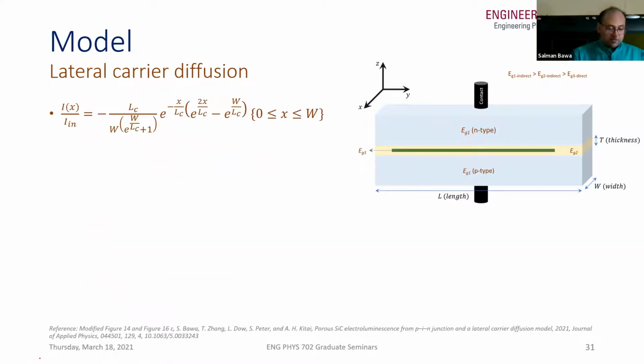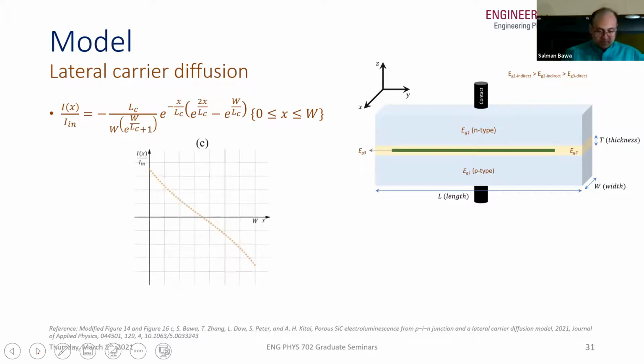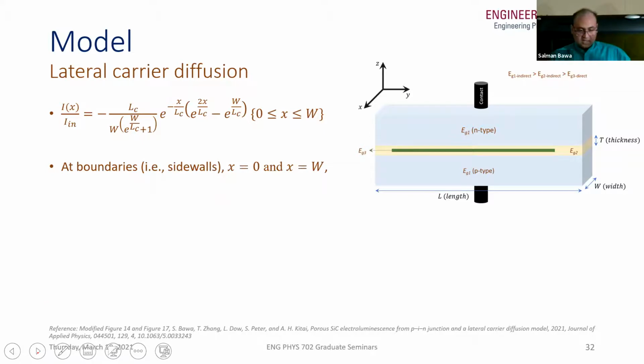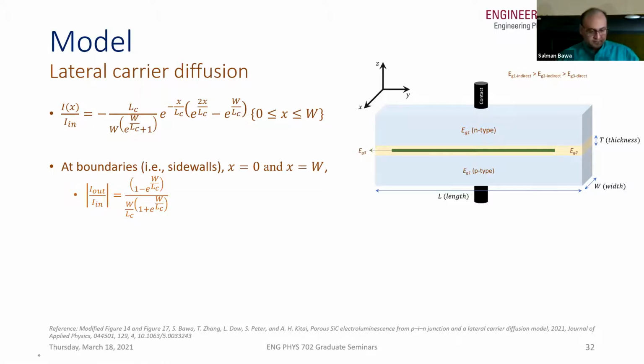We take this equation and we plot. And once again, we get what we expect, that at the center of the device, the ratio is 0, and the ratios are maximum at either edge of the device. Now we want to go into the boundaries itself. So at x equals 0 and x equals w, let's put that into this equation of the ratio of the current density to the input current. And what we get is this equation that you see on the screen.